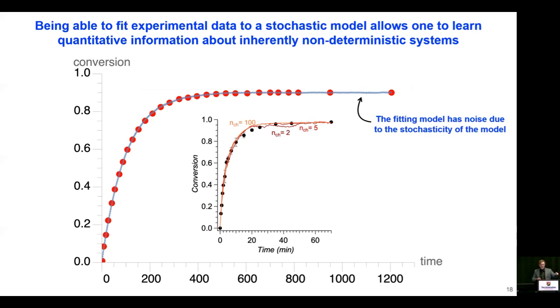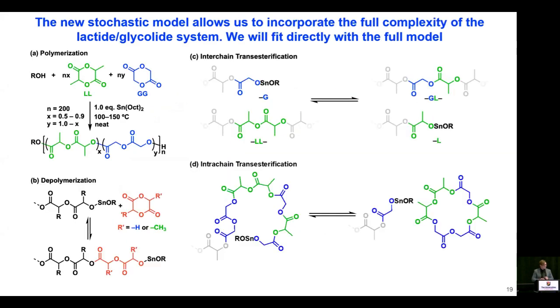And you'll notice that our fitting curve has noise, which is interesting, right? But that is as a result of the stochasticity of the calculation that we're doing. If we simulate a smaller solution size, then we have more fluctuations, but it is fast. If we simulate a larger one, we have less noise, but it is slower. And so you have to navigate these two things as you're fitting it to your experimental data.